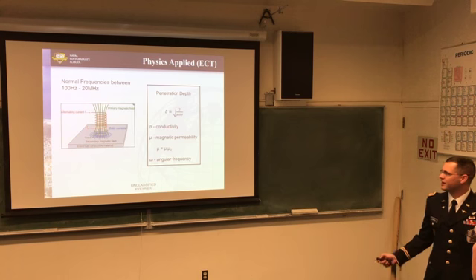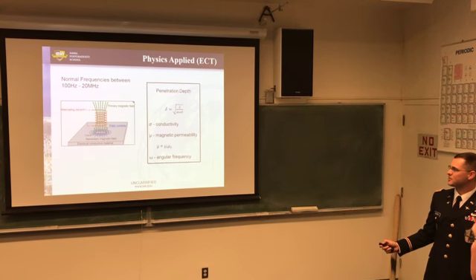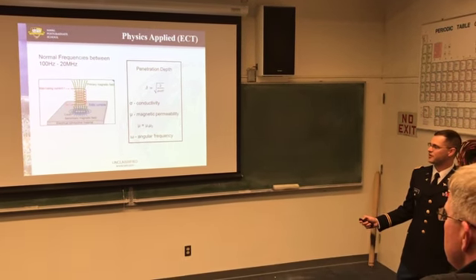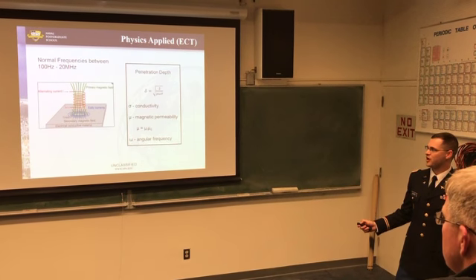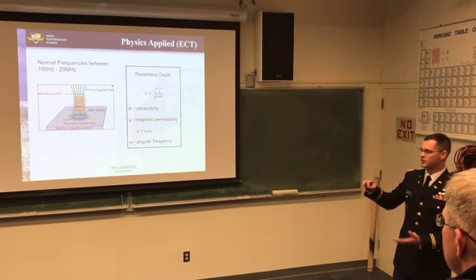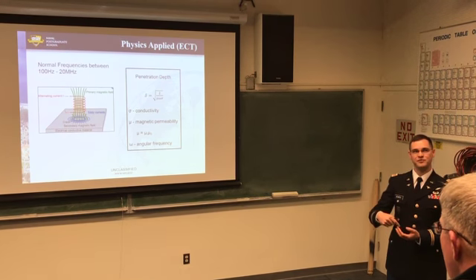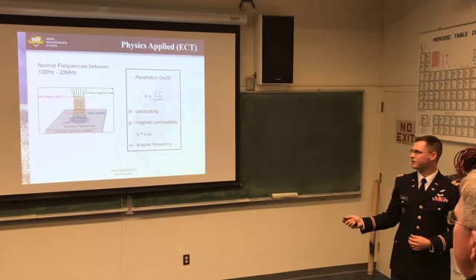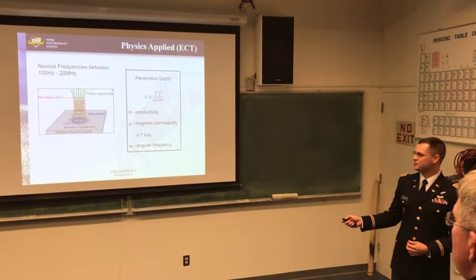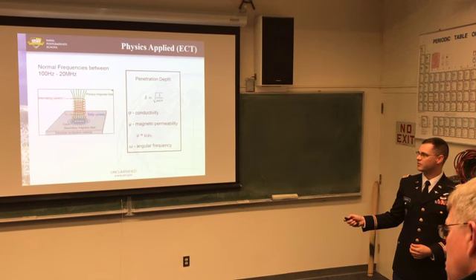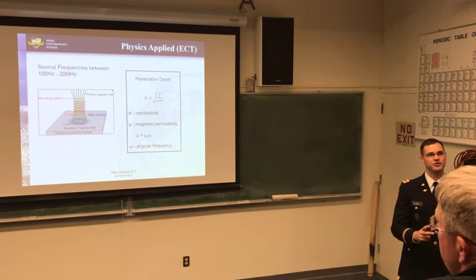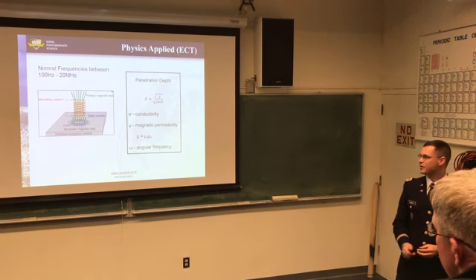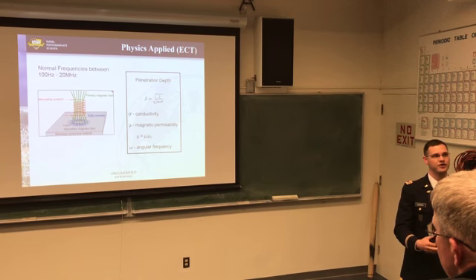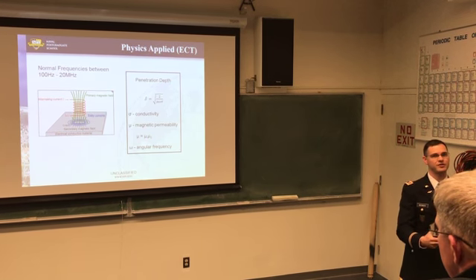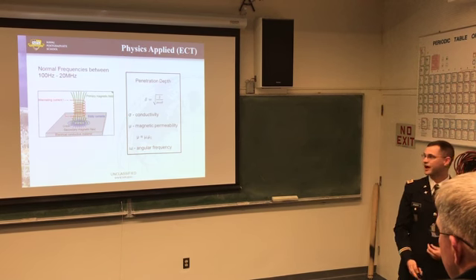So eddy current testing, this is kind of a picture of how eddy current testing works. You put an alternating current in a coil of wire. It induces a primary magnetic field, and then when you get that close to a material, that magnetic field induces eddy currents. So it's a secondary electric field induced by your magnetic field, and those eddy currents produce a secondary magnetic field, and then when you calibrate it, it has a characteristic impedance of the entire system. So when you come close to a defect or a crack or something like that, it will change the impedance and let you know that something's going on and requires further inspection of the reactor.